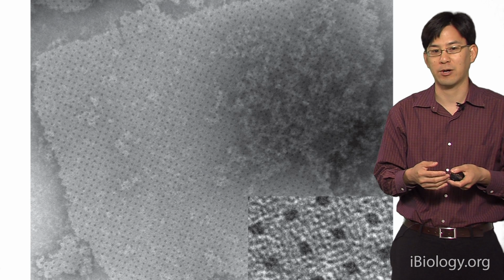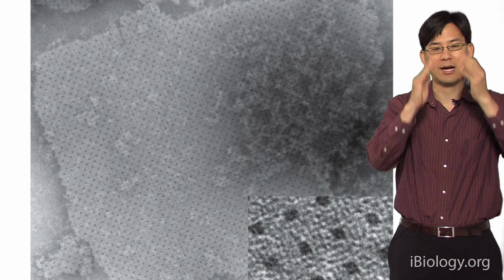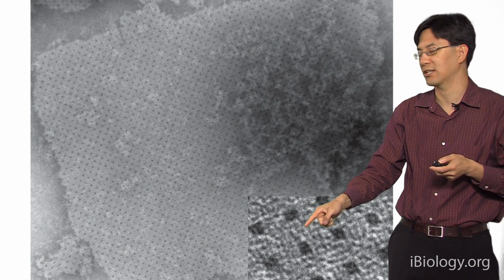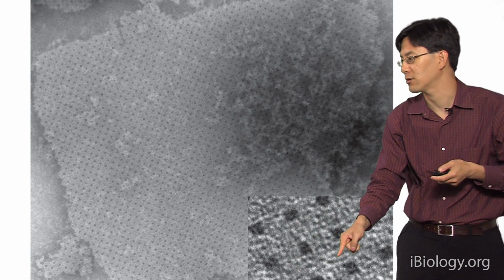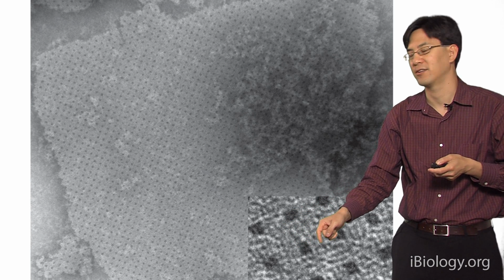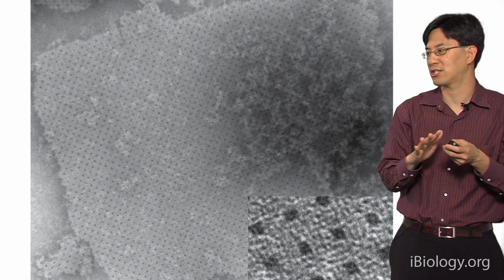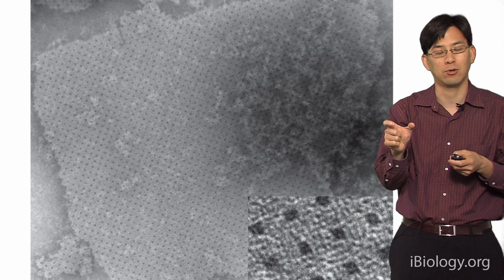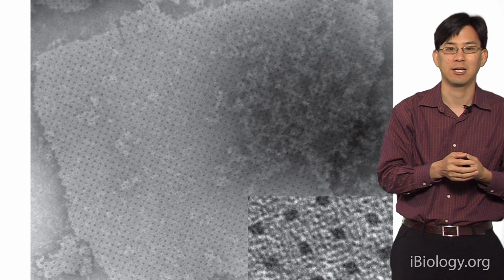So this is a quite remarkable design that was developed by Yonggang, where the helices are pointing up out of the plane of the DNA crystal, and the unit cell has dimensions of 6 helices by 6 helices, so about 15 nanometers by 15 nanometers. And in this particular example, he designed a cavity within the unit cell of 2 by 2 helices that are missing. And then this is going to self-assemble into a crystal where, again, the unit cell has dimensions of about 15 nanometers, the hole's dimensions about 5 nanometers, and the entire crystal can grow to multiple microns in dimension.